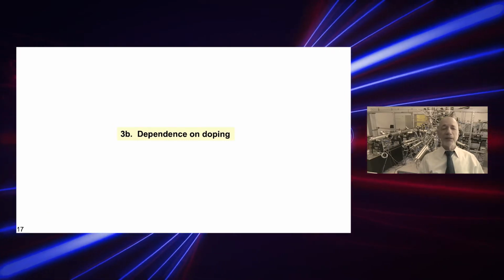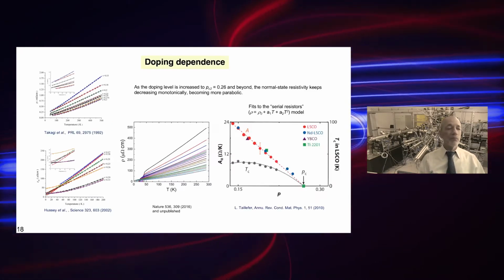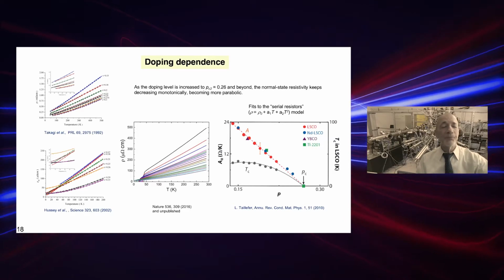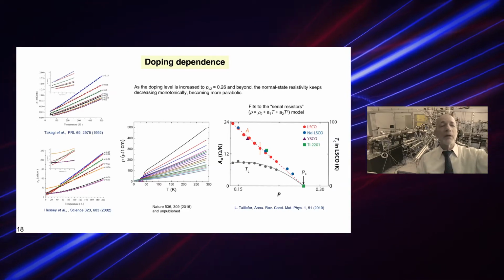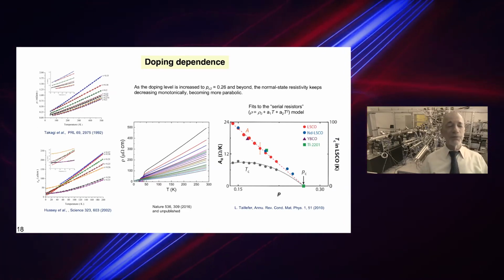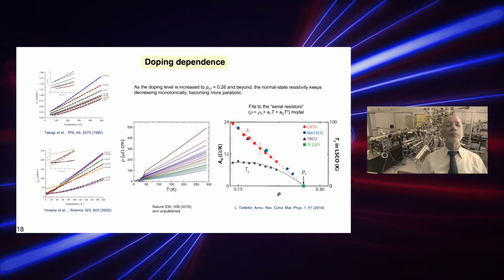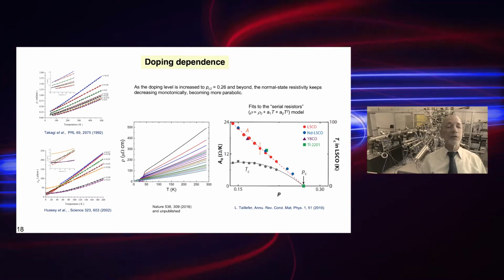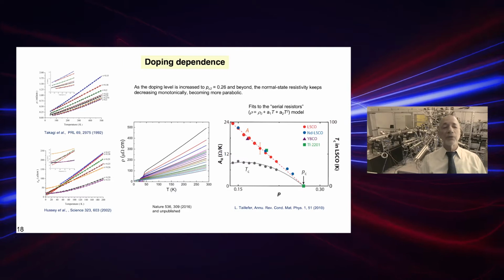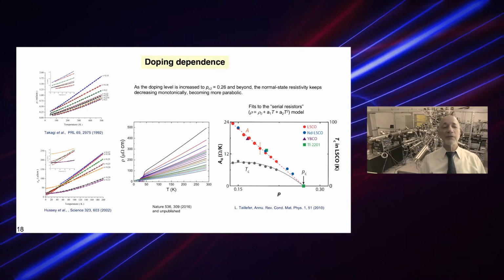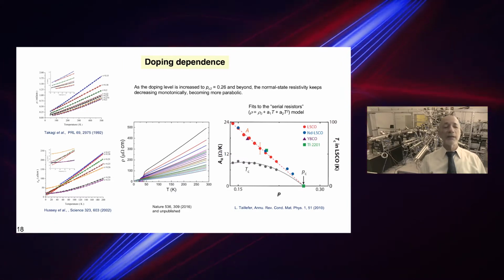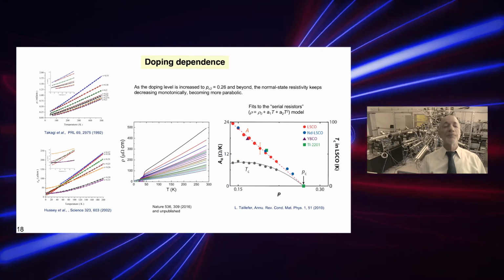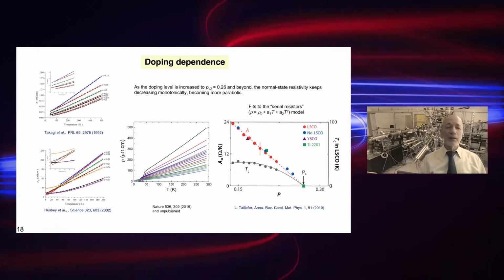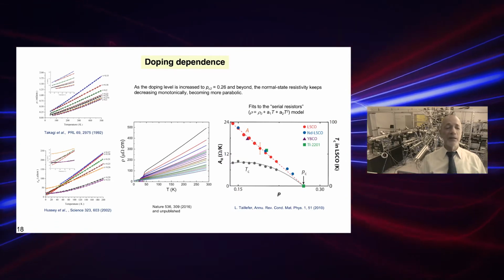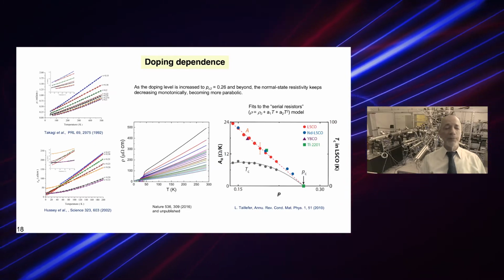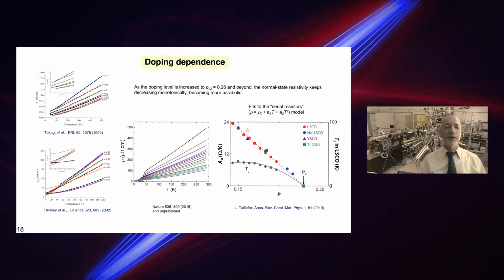Let's look now at the dependence on doping. So here are sets of data for lanthanum strontium cuprates doped to very different levels. You can see that at high temperature, the dependence turns out to be linear. At low temperature, high doping, there is more of a parabolic dependence.